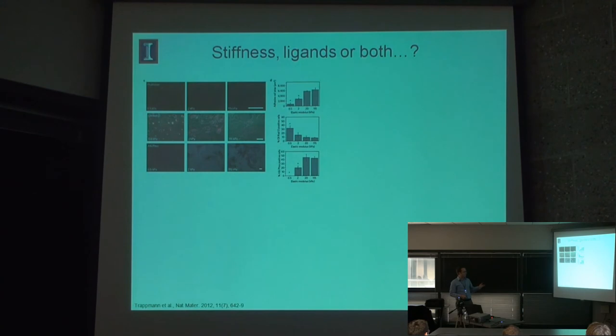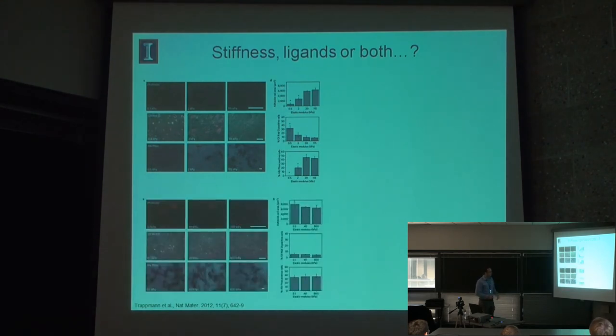And so this is consistent with this argument that there's lineage matching between the differentiation outcome and the mechanics of the material. But then they went and used PDMS, which doesn't have a porosity component. And they showed that when they modified PDMS of different mechanical properties, they saw no difference in the number of cells, no difference in adipogenesis, and no difference in osteogenesis.